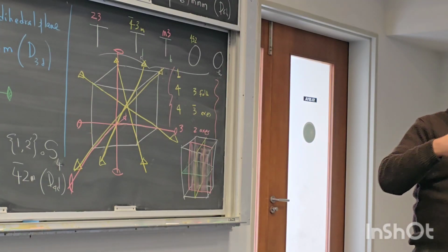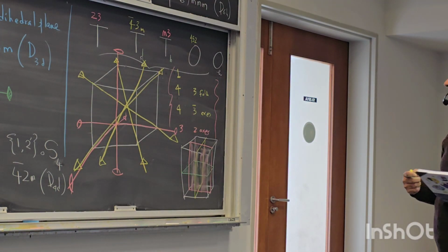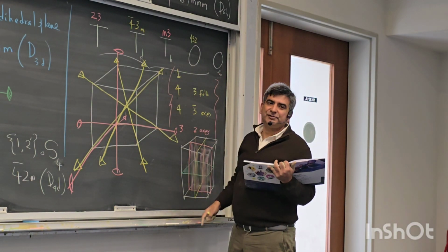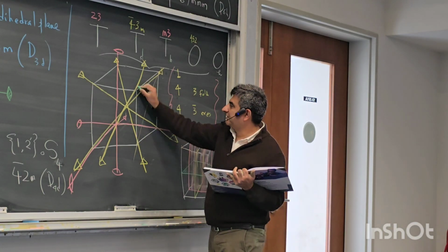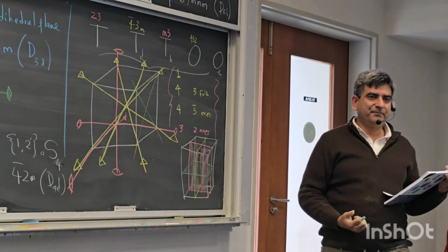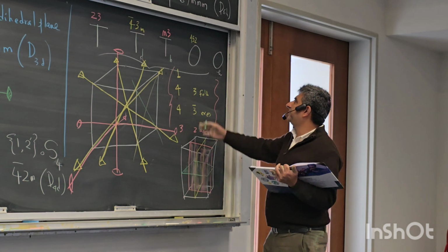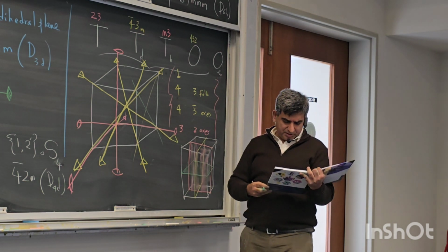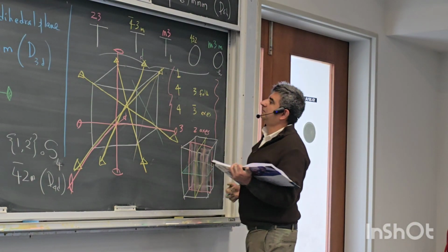Whenever there is a 3-fold axis of rotation, remember there is always a 3-bar axis of rotation as well. Additionally, along the face diagonals, it has 2-fold axis of rotation on this face diagonal, along this face diagonal. This will qualify this as an octahedral symmetry cubic group. And if you add these 3 mirror planes to O, you get the Oh group, which has a symbol m3m.